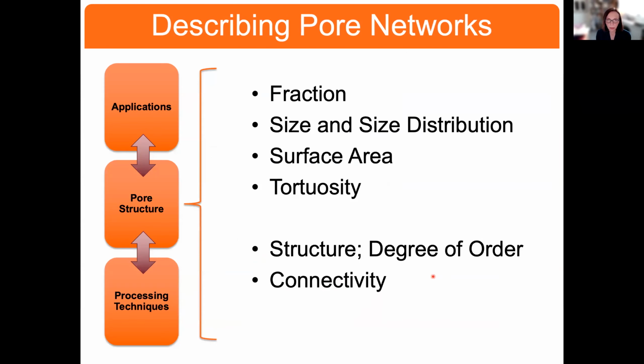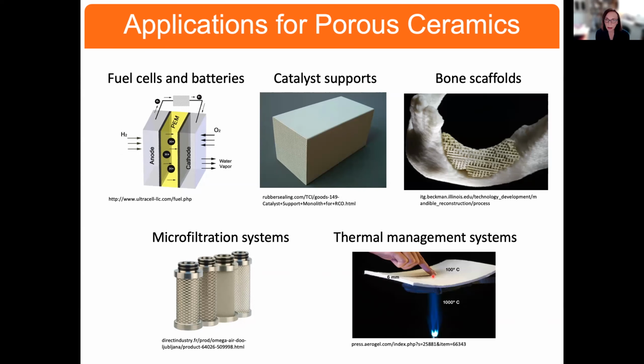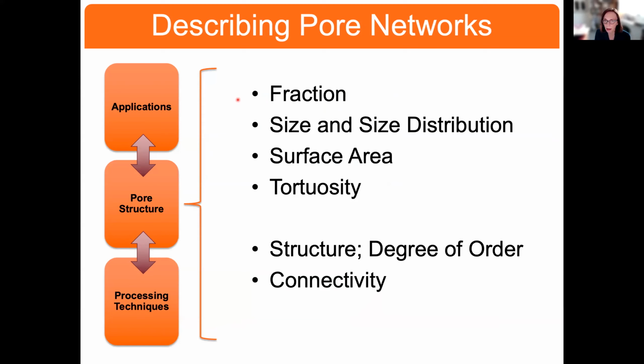With that in mind, we need some sort of way to describe these pore networks, because, as you saw in this previous slide, these pore arrays can have a variety of shapes and sizes. It's not just how much porosity is there, shown here in terms of fraction, but we also need to think about pores in terms of their size distribution, their surface area, their tortuosity in a specific application in which the pore pathway can be quite rough. And in fact, we can get a measure of that: the degree of order in the pores.